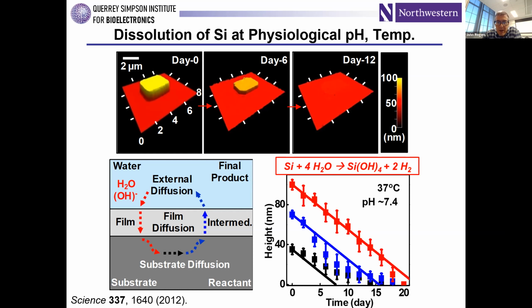Very slow chemistry here, a couple of nanometers per day in terms of dissolution rate, but definitely very important chemistry in the context of thinking about a building block material, a semiconductor material for these envisioned water-soluble electronic systems. The bottom right shows the time dependence of the thickness of these nanoscale platelets of silicon as a function of time in days. In about 3 weeks, you lose about 100 nanometers, something like that.